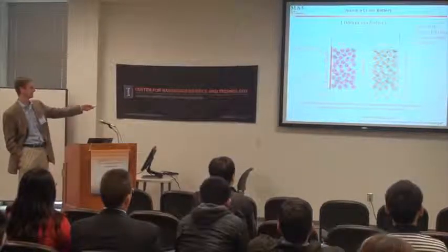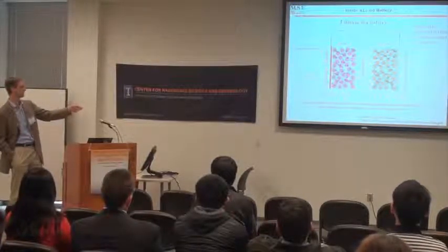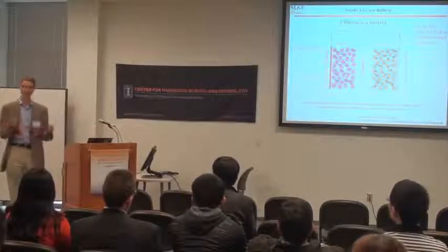So if we zoom in inside the battery, and this happens to be during the charging cycle here, the anode is typically a carbon-based material. Electrons can be inserted into that as well as lithium ions, and so the lithium is stored very close to the metallic state. And as you know, metallic lithium is high energy, lithium salts are low energy. So as the battery charges, the lithium is converted into its near metallic state and stored in the carbon. As the battery discharges, the lithium ions come back into the cathode, where it's stored primarily in an ionic form. And so that's what a battery is doing. It's shuttling lithium between two different oxidation states and electrons through the outside circuit. And what I'd like you to recognize here is that you have to not only be able to efficiently move the lithium, you have to be able to efficiently move the electrons.